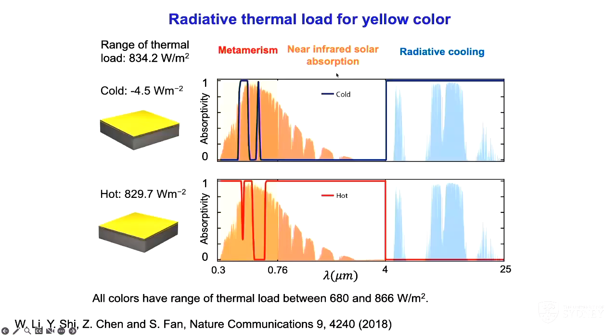So if you want a cold structure, you want something that radiates very strongly in the mid-infrared. You don't want it to absorb any near-infrared solar radiation, and you also play with the visible part of absorption. And conversely, you can design a hot structure. What he showed theoretically is that under the sun, the thermal load of these structures differs by more than 800 watts per meter squared. To put that number into context, the entire solar energy that you have is about 1,000 watts per meter squared. So this is a very large swing in terms of the thermal load.